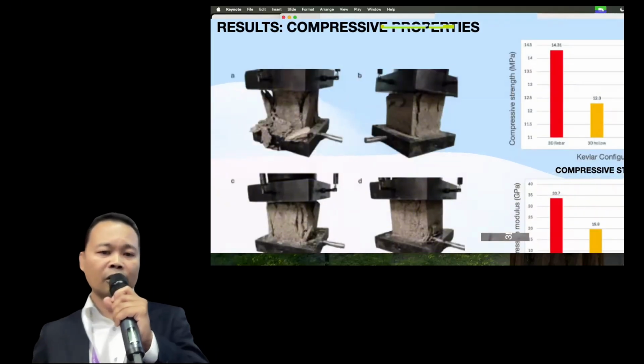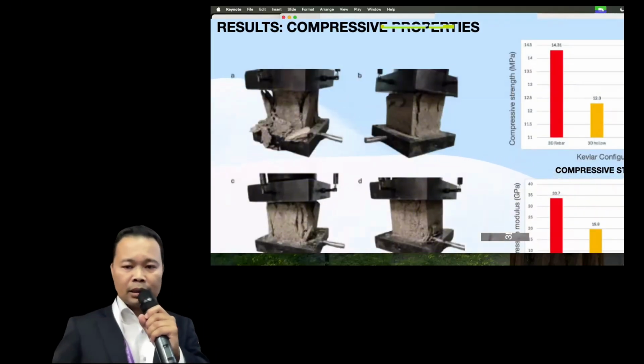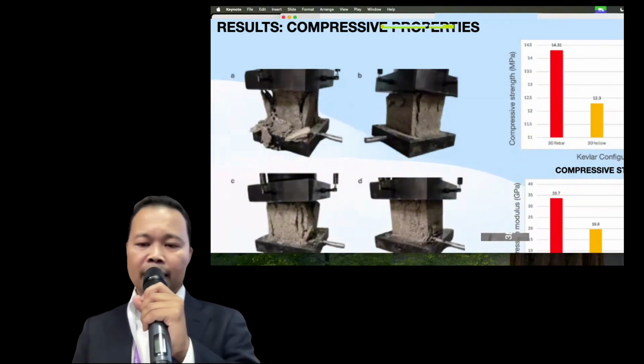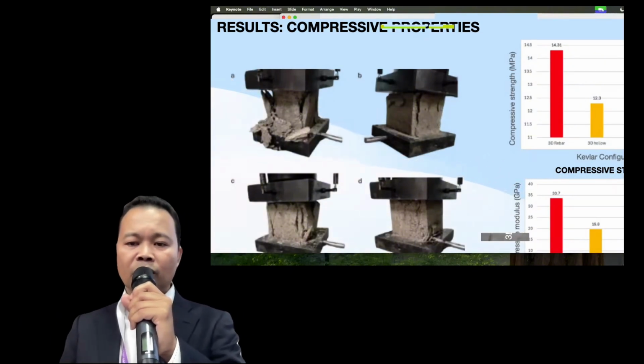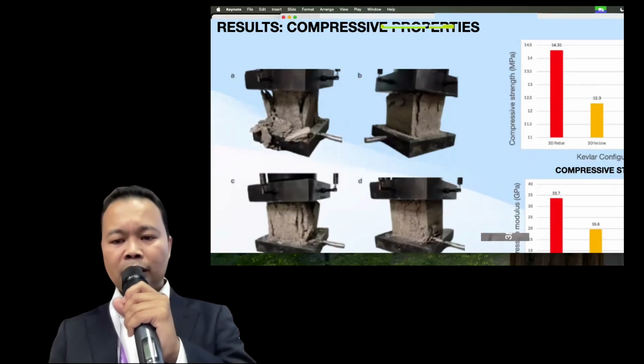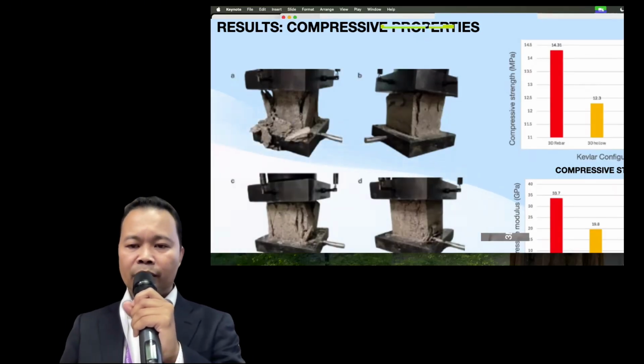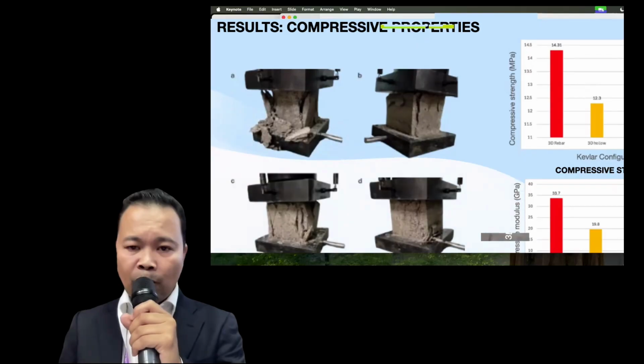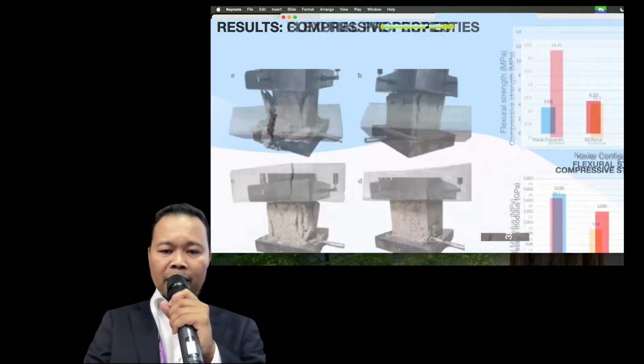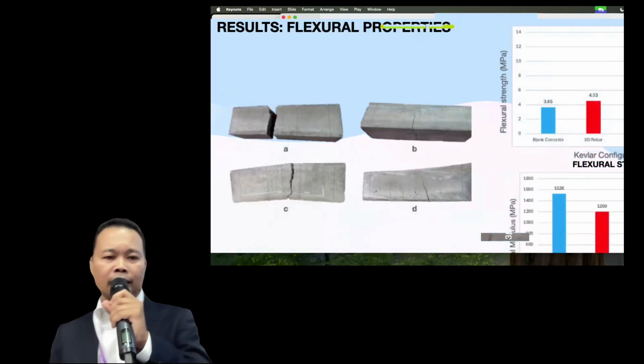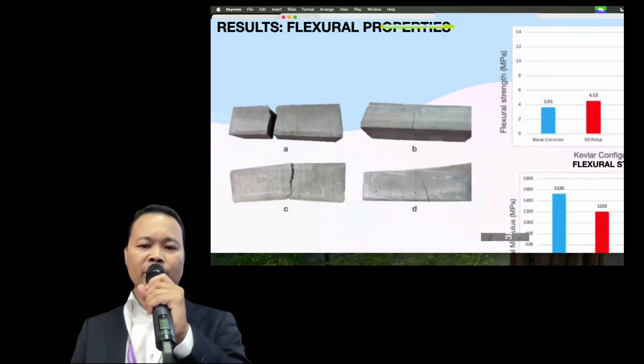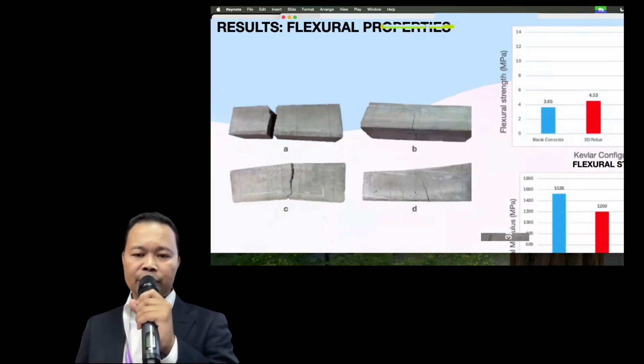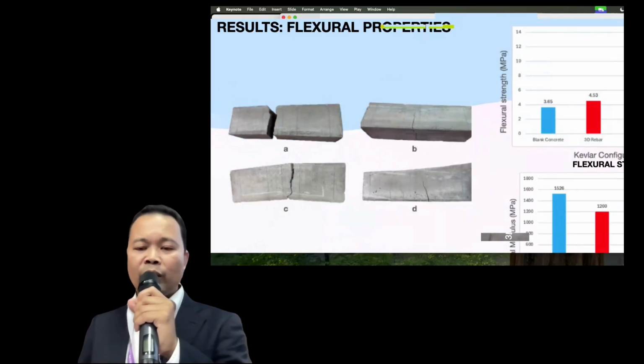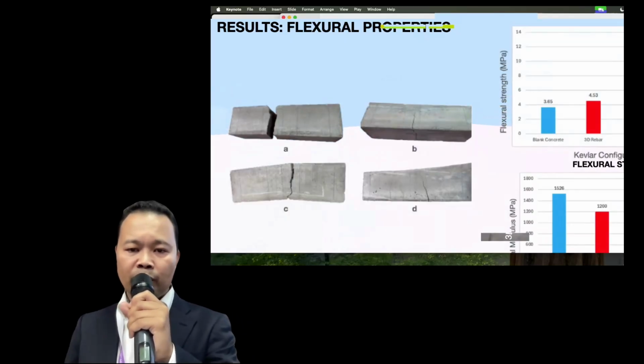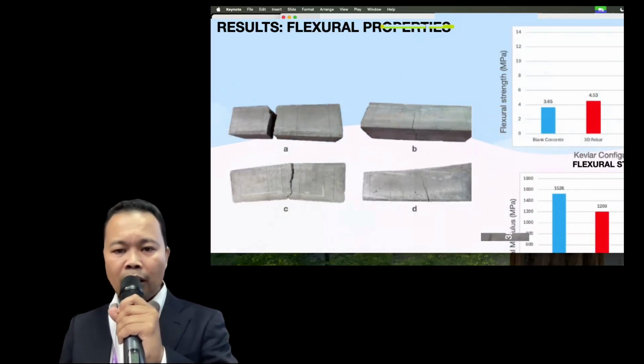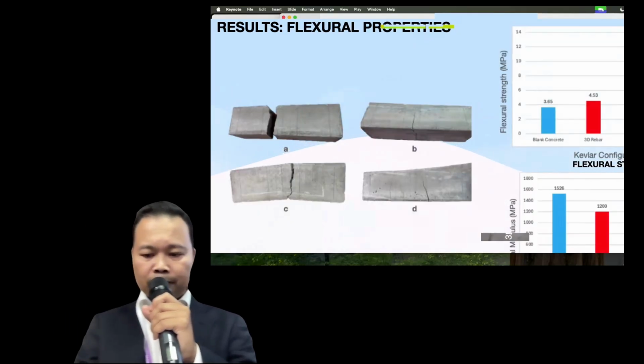And here is the result of the compressive properties. So we can see here it looks like there is no strong correlation between the configuration of the fiber and the compressive strength. But we can see from here that in the case of the flexural properties, there is a strong correlation between the configurations of the fiber and the flexural strength of the composite.